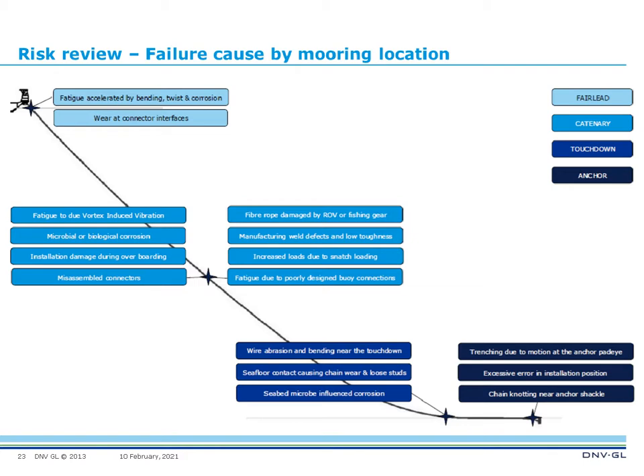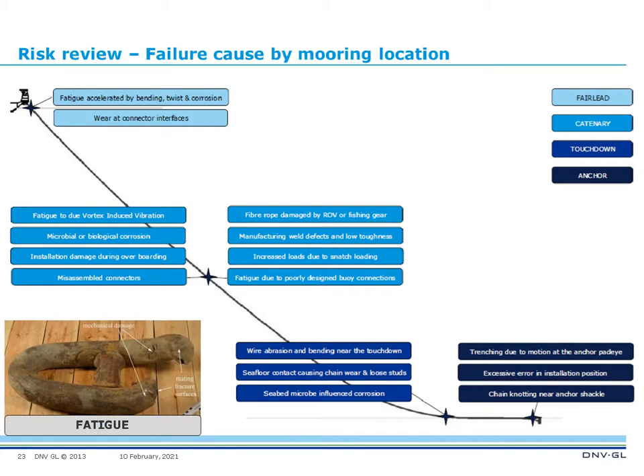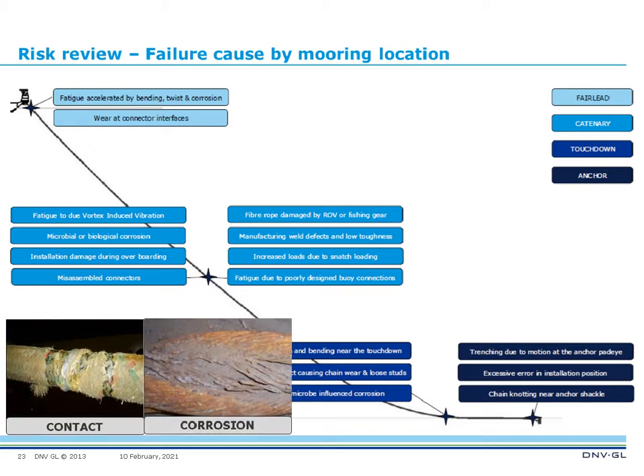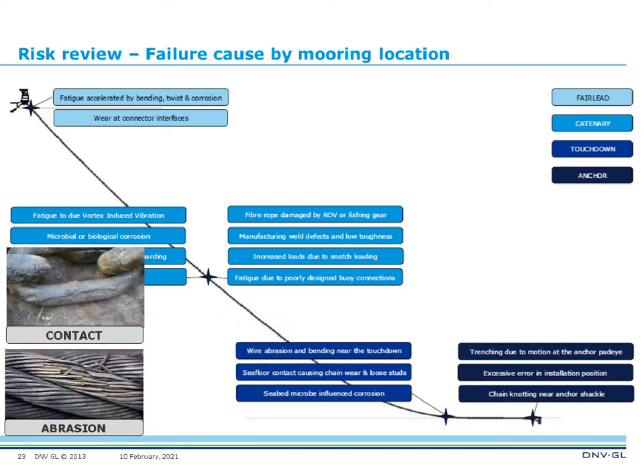We can also categorize failures by location of the mooring system. The combined tension and bending fatigue seen in the North Sea failures typically occurs close to or at the fairlead. In the midwater column, we've observed issues due to accelerated corrosion or contact damage, such as with fishing gear or ROV. At the touchdown point, there have been observations of contact damage as a result of improper survey, missing out boulders, or, as mentioned before, due to wire rope being in contact with the thrash zone, where bending and abrasion can cause relatively rapid failure of such components.